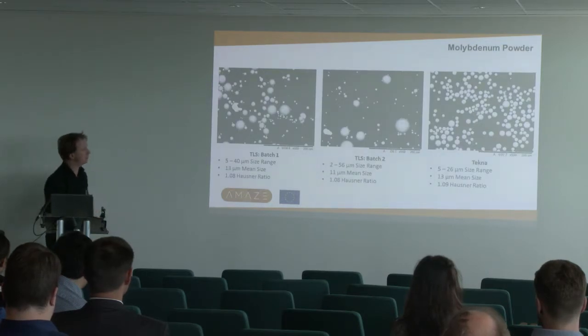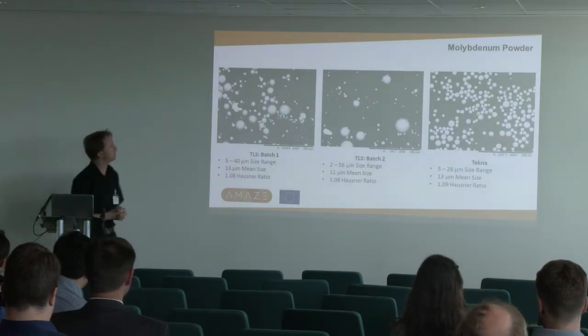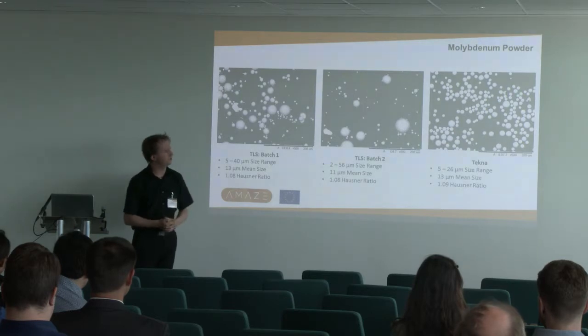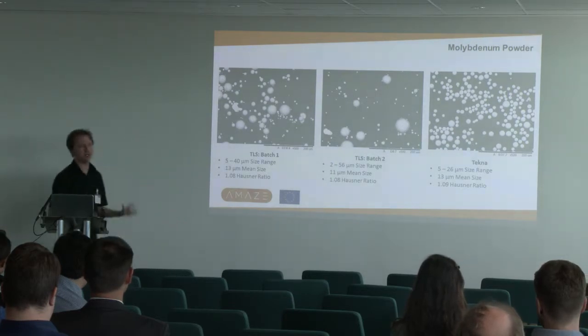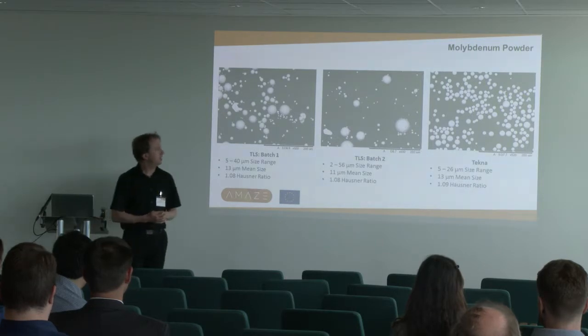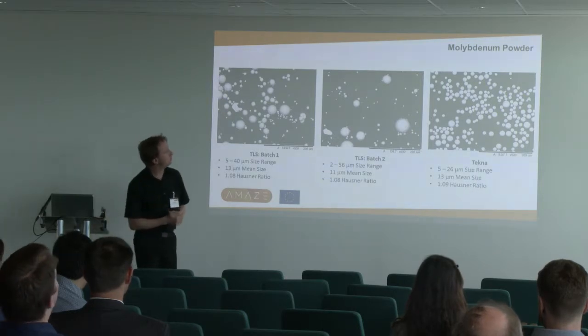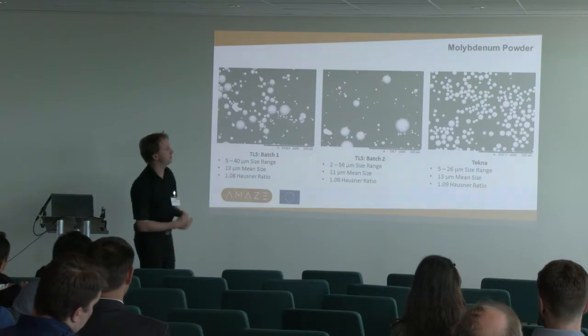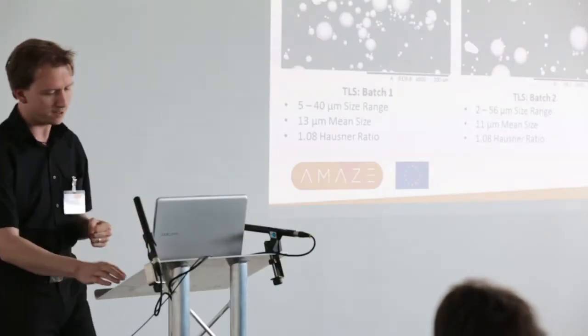So here are those 3 different powder batches. We had 2 from TLS, which showed quite a lot of fines. They didn't spread very well in the machine. The fines tend to agglomerate the powder a little bit, sort of cakes up. And then we had a nice spheroidized powder there on the right-hand side from Tekna.